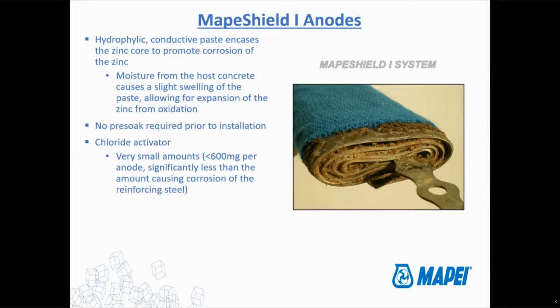They do use a chloride activator. So some of the specs you'll see, there's one competitor. All the anodes on the market use chloride activators except for one. And that competitor is very aggressive with their specs. So they'll have a lot of specs that say you can't have any chloride or any deleterious material to concrete. Folks, we're talking about adding like a pinch of salt to the ocean is essentially the amount of chloride you're using. It's not a big deal. Everybody's anodes, frankly, are doing it. It's not going to leach out into your concrete. It's not going to cause more corrosion in your deck. It's all going to be confined to this anode for as long as it's there. So it's really not a big deal.